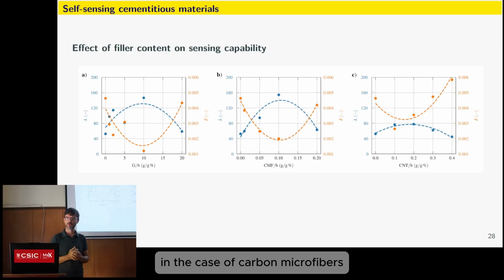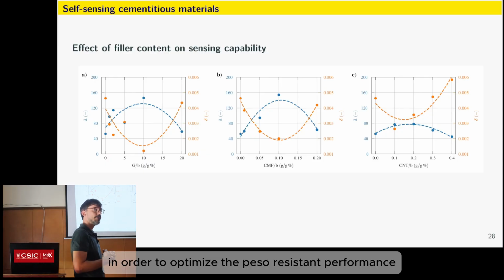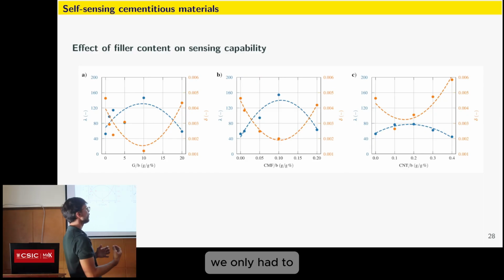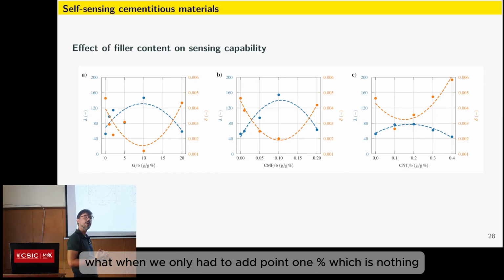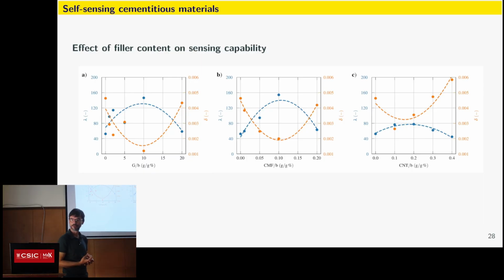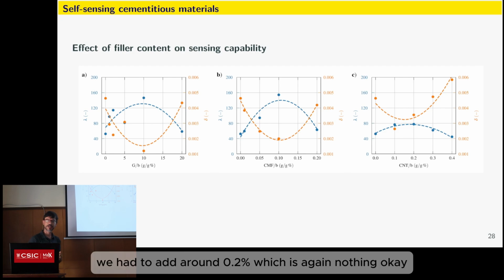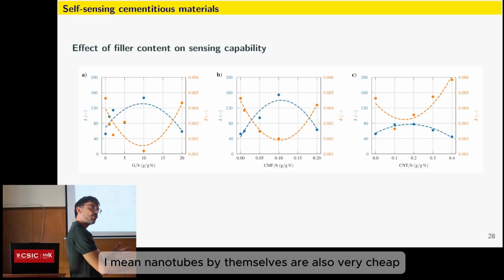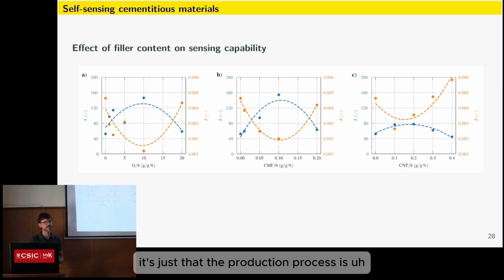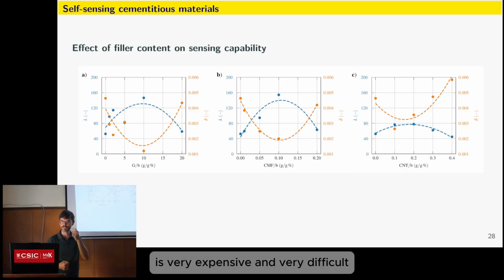In the case of carbon microfibers, in order to optimize the piezoresistive performance, we only had to add 0.1%, which is nothing. In the case of nanotubes, we had to add around 0.2%, which is again nothing. Nanotubes by themselves are also very cheap. It's just that the production process is very expensive and very difficult.